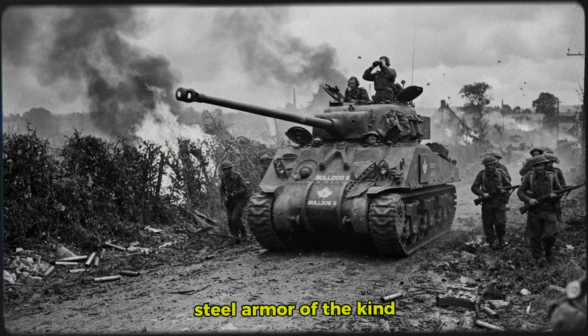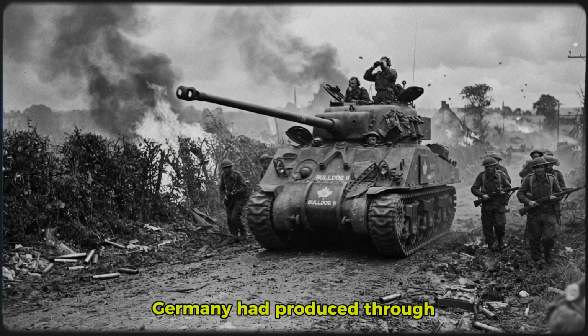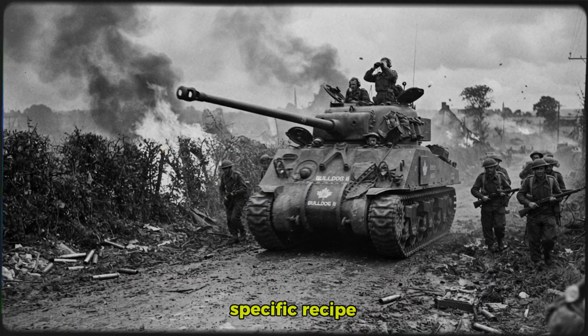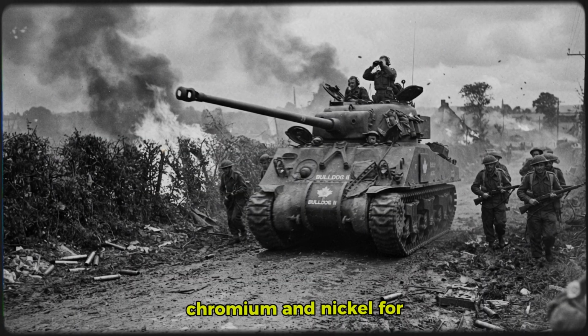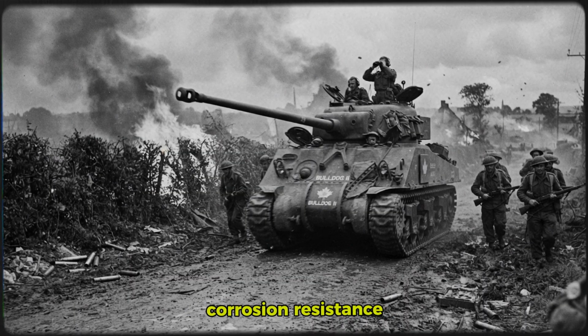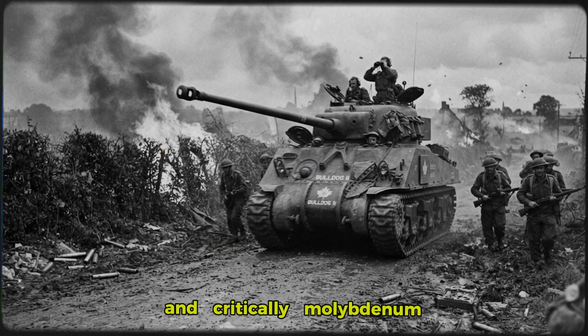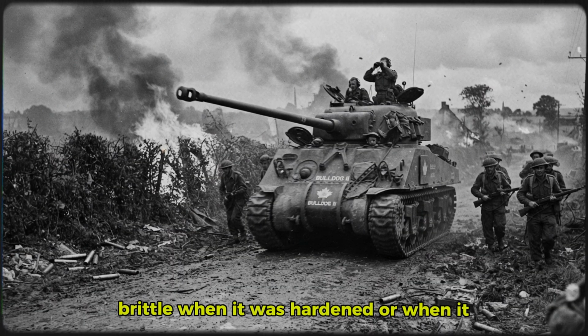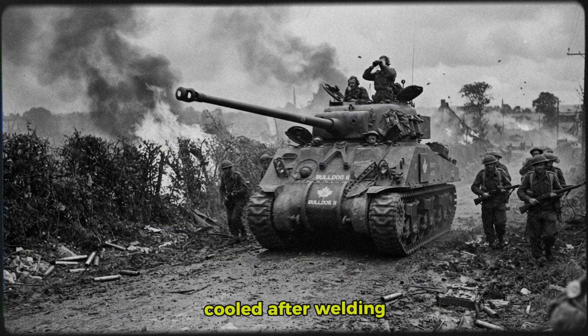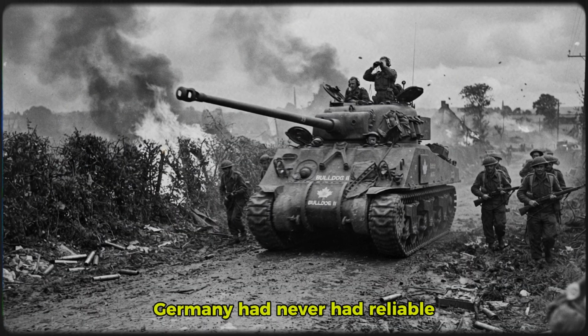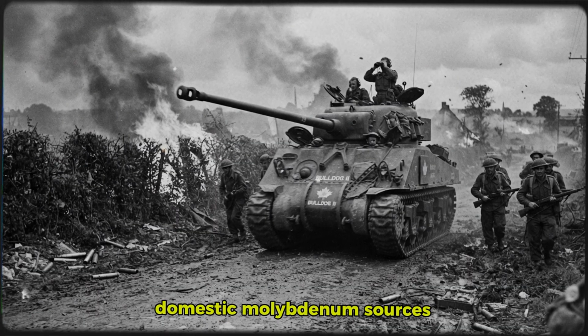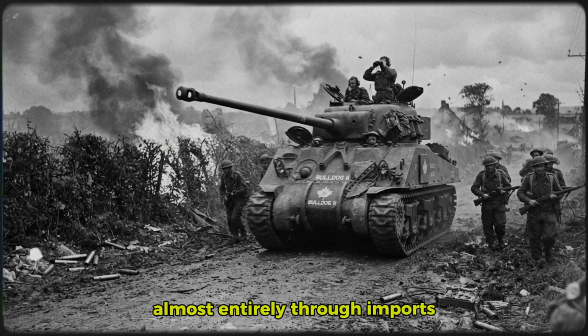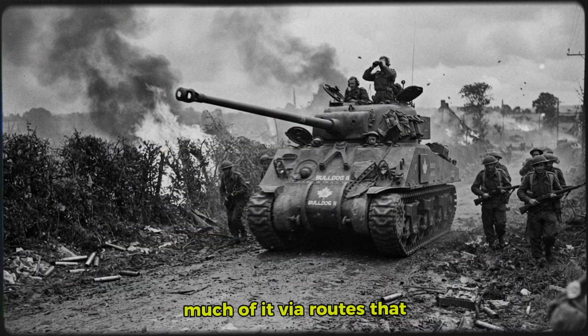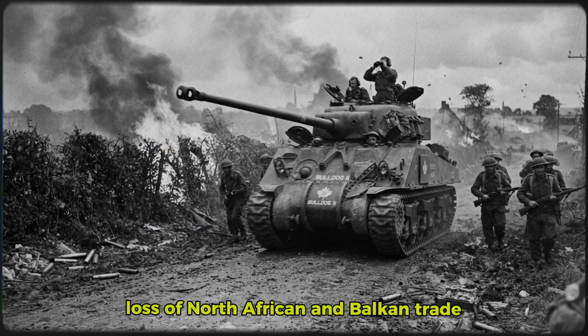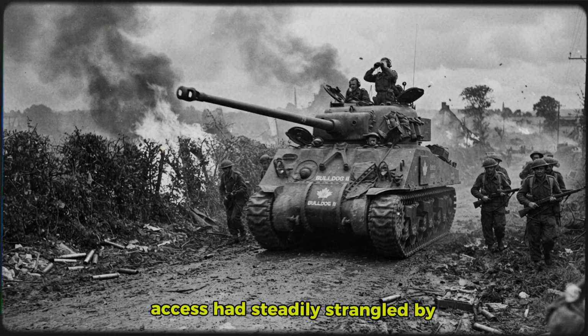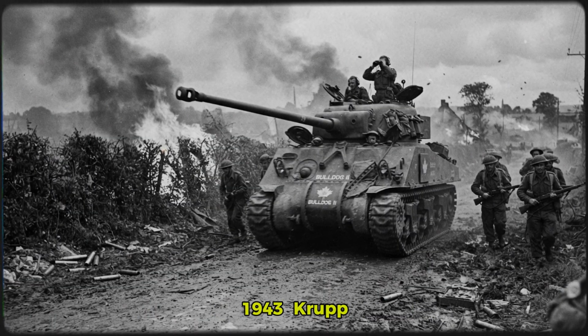Face-hardened and homogeneous steel armor of the kind Germany had produced through 1942 depended on a specific recipe: chromium and nickel for toughness and corrosion resistance, and, critically, molybdenum, which prevented the steel from becoming brittle when it was hardened or when it cooled after welding. Germany had never had reliable domestic molybdenum sources. Its pre-war supply came almost entirely through imports, much of it via routes that Allied blockade and the loss of North African and Balkan trade access had steadily strangled by 1943.